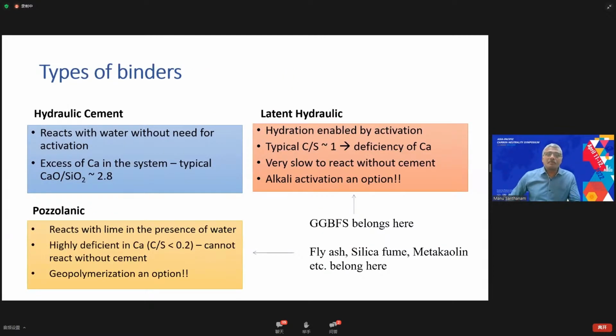When moving from cement towards other types of binders, the chemistry has to rely on reactivity we call pozzolanic reactivity, where alternative materials react with the lime available in the cement. There's a certain degree of lime availability that dictates the amount of reaction that can take place, so we're primarily looking at pozzolanic binders that can enhance the quality of cement in the long run.